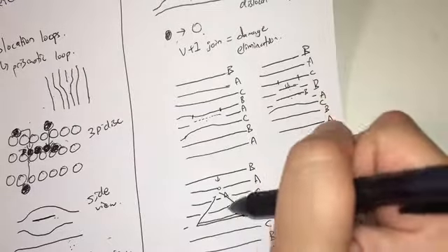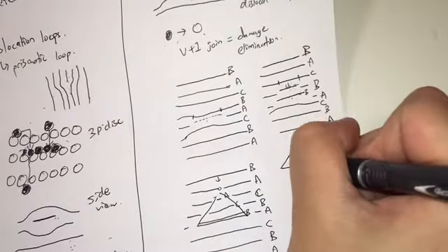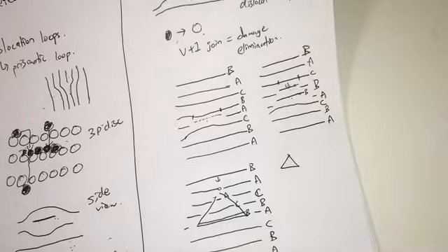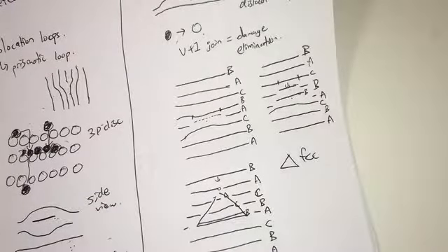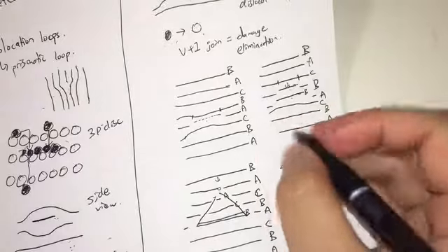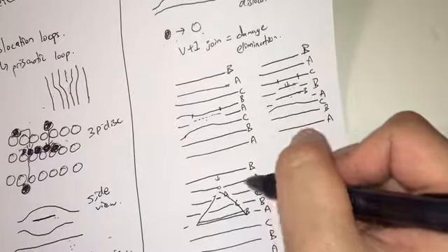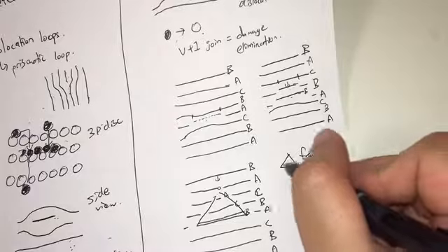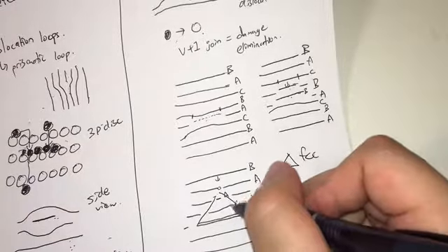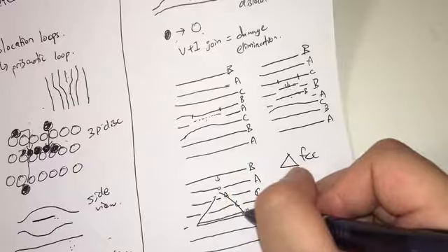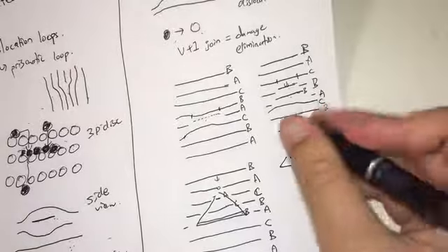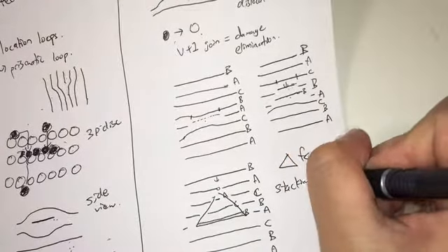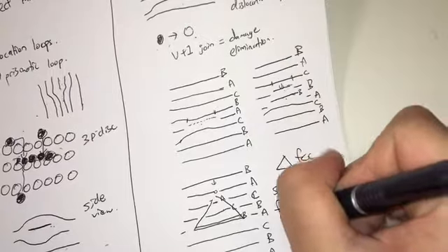So these dislocation loops may not be circles, they're actually, you know, like triangle shape, tetrahedral shape, because that's the most stable configuration for an FCC structure. In BCC this may not be the case, but for FCC that's certainly the case. So what you have is this shape where at the bottom is a triangle shape, and each side is a triangle shape as well, so that it's a large triangle at the bottom, followed by small triangles, followed by smaller and smaller triangles, so that what you have is a stacking fault tetrahedron.